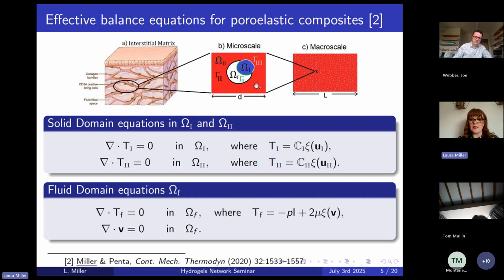Here I have three different domains. Omega 1 is my solid elastic fibre, and omega 2 is my solid matrix. Let's put down some equations for those solid domains first. I have a balance of my two stresses, where T1 and T2 are the stress tensors in each of those compartments, given by C1 and C2 respectively, which are the fourth rank elasticity tensors of each material phase. These are applied to the symmetric part of the gradient of the elastic displacement U1 in the fibre, or the elastic displacement U2 in our solid matrix. So these are our two solid stresses.